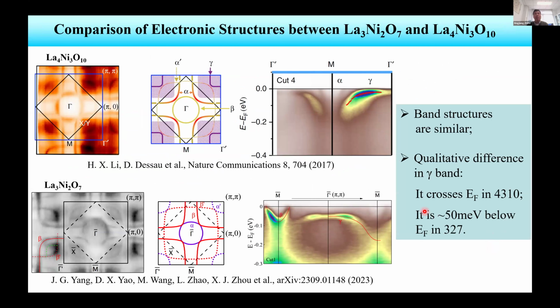Then eventually I also want to compare our results on 327 with that of 4310. This is the result that Professor Dan Dessau's group obtained in the 4310 system, and this is the Fermi surface mapping. This is the central one, this is another one, and the third one is the gamma Fermi surface. In the 4310 case, in this region there is a flat band that crosses the Fermi level, and that gives rise to this gamma Fermi surface here.